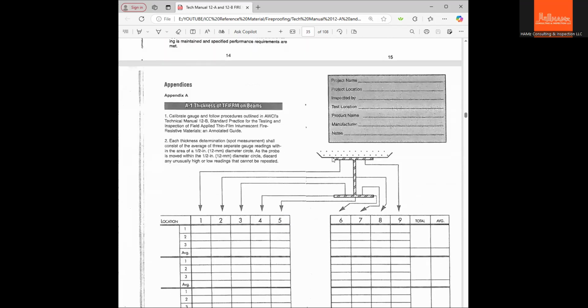So this is for the beams. As you can see, you cannot measure the top of this because it's supporting the slab, the ceiling. So we're going to start measuring the thickness from the bottom surface of the top flange, then the web, the top surface of the bottom flange, the tip, the bottom. At this particular area, it's very hard to maintain the thickness because as this material goes thicker, it's going to be heavier, and for the guys to maintain that thickness, they need to wait a lot of time to cure the paint for it to stick on this area.